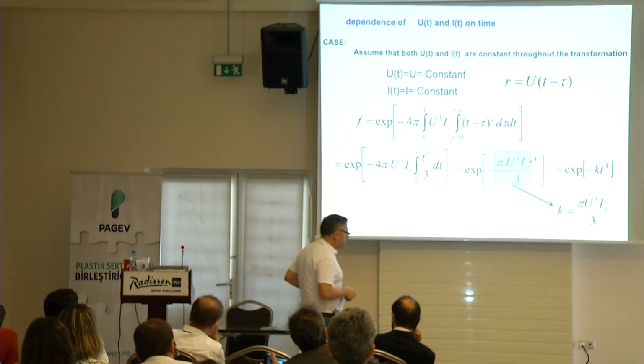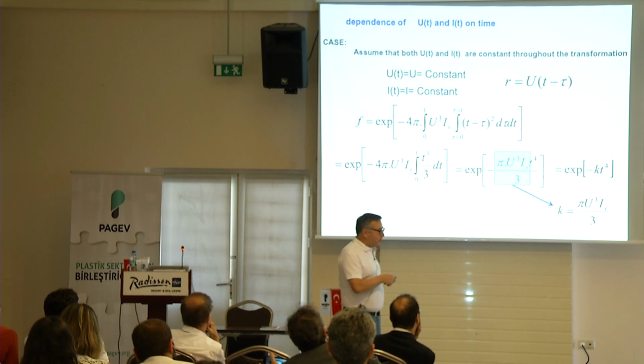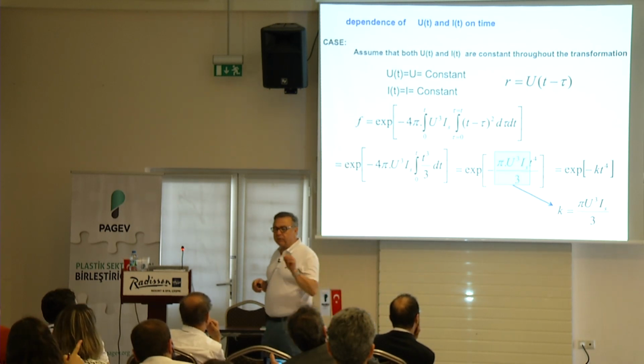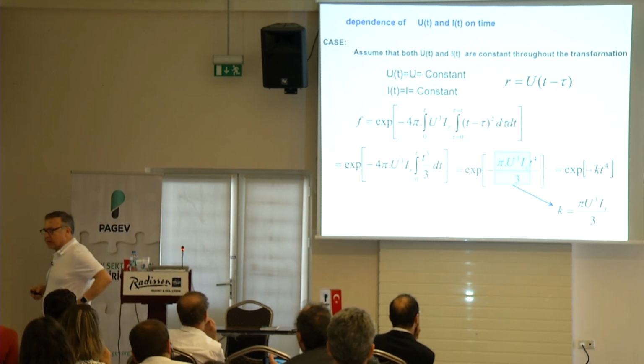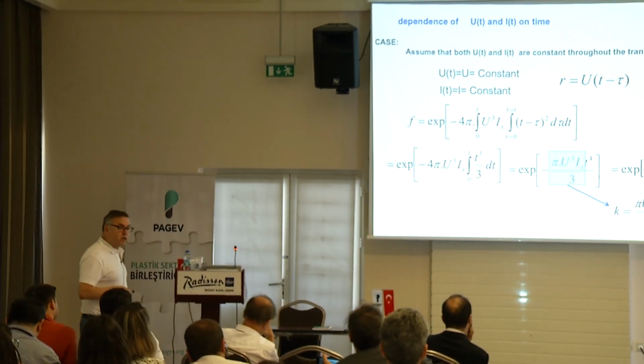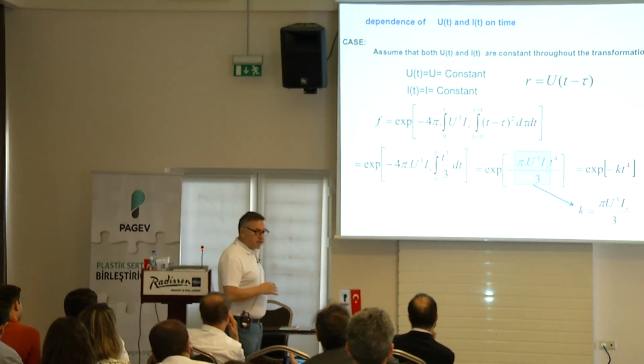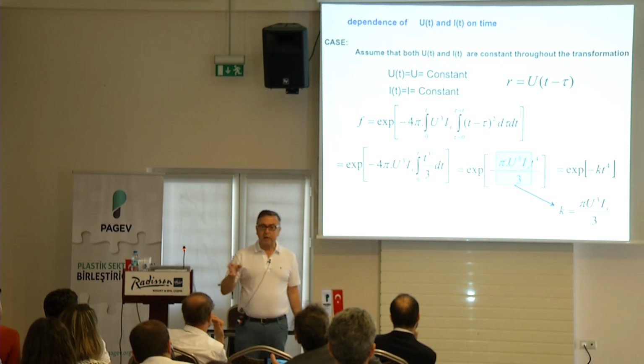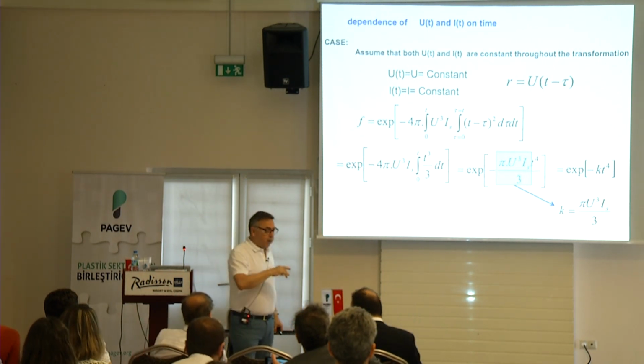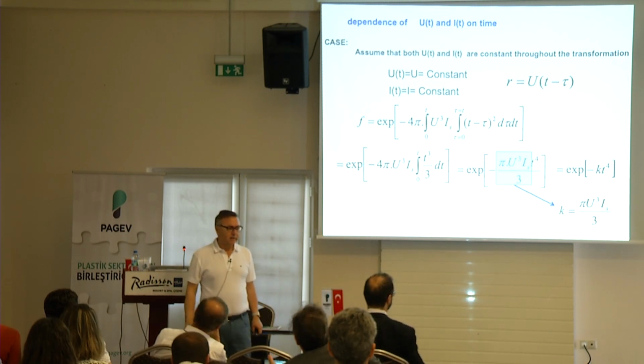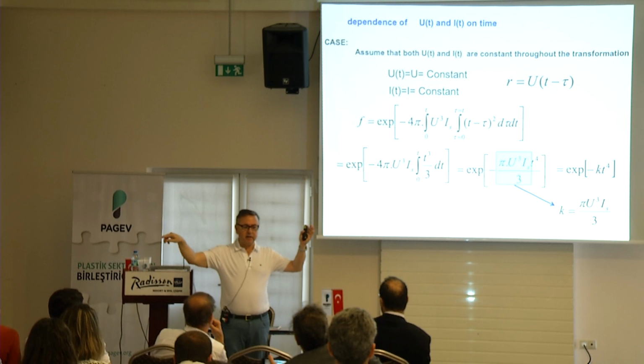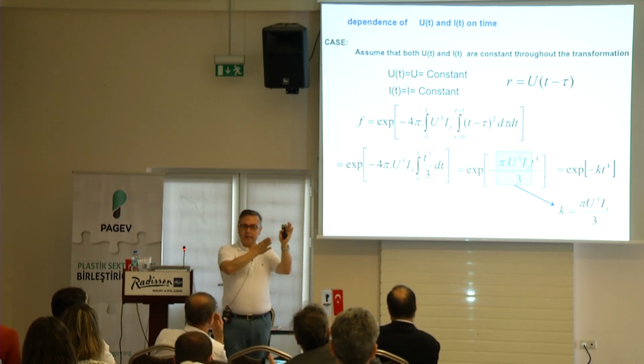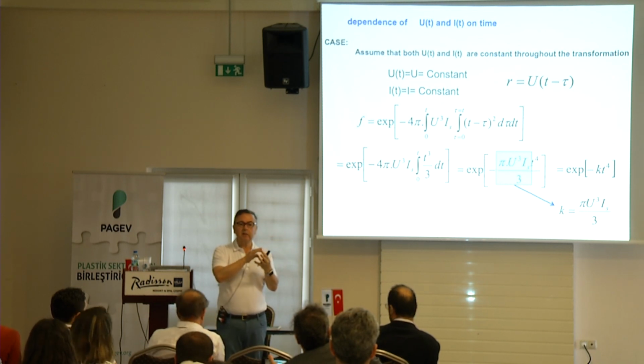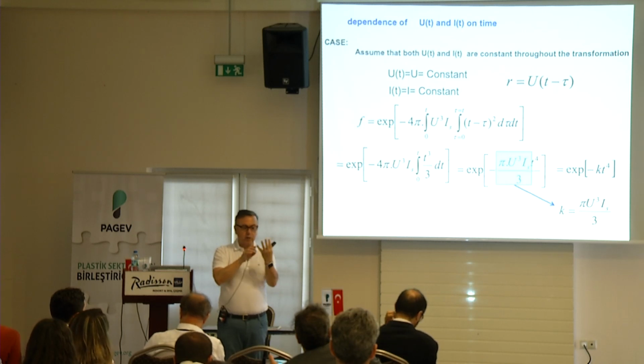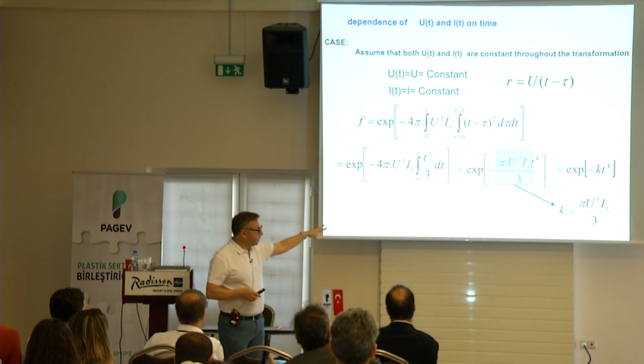Rate constant. It's an exponential term. I want to give you 2 points on this relationship. One is the nucleation rate, and the other one is the growth rate. And I want to connect it to something practical for you to take away. Growth rate, we already discussed. Remember what controls the chain attachment to the growing crystal? We discussed it. What was it? Molecular weight, viscosity, temperature, pressure, all of that. So these are the parameters that you can use to control the growth rate.